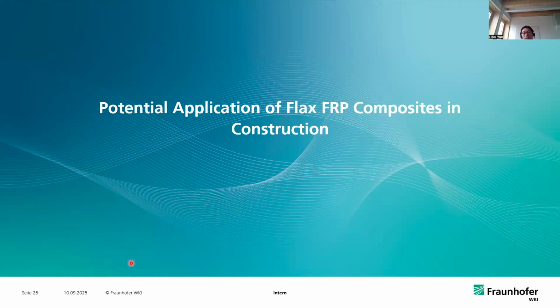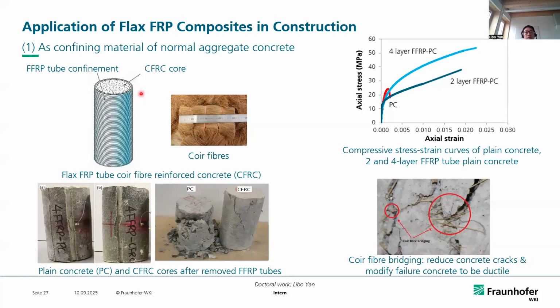After exploring the mechanical performance of flax, we move on to the potential application of flax fiber reinforced polymer composites in construction. What we can learn is that their sustainability and performance can bring real impact. One of the promising applications of flax FRP composites is in so-called concrete-filled FRP tube structures. The flax FRP serves as the cast-in-place formwork for the fresh concrete and also provides additional confinement to the concrete. The core can be further reinforced with natural fibers like coconut fibers.